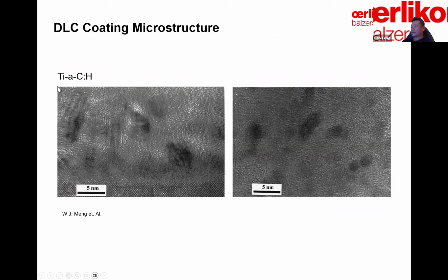This is titanium doped amorphous hydrocarbon, or titanium DLC. This is a cross-sectional high-resolution transmission electron microscope micrograph. You can see the atomic level resolution here, and those clear lattice fringes representing the titanium carbide crystals. On average, they are about 2 to 5 nanometers in size, embedded in an amorphous carbon matrix. So this is proof of this nanomaterial. Look at those clear lattice fringes, really impressive.